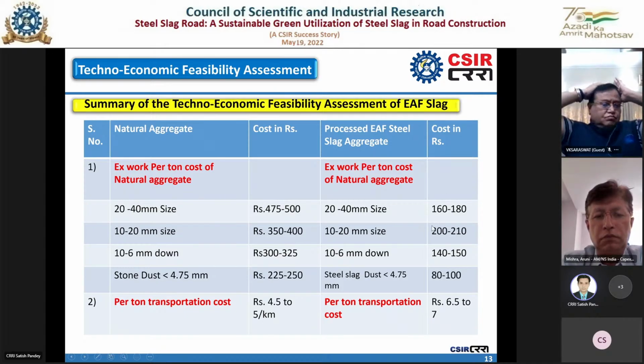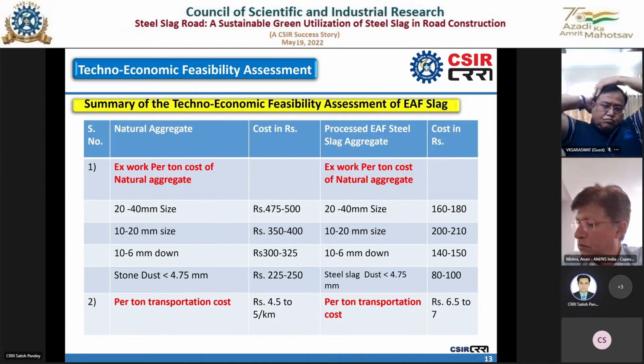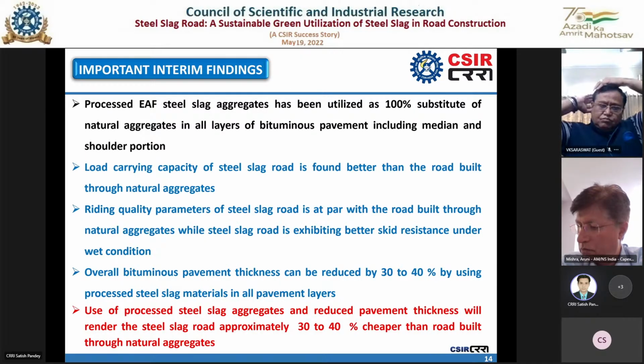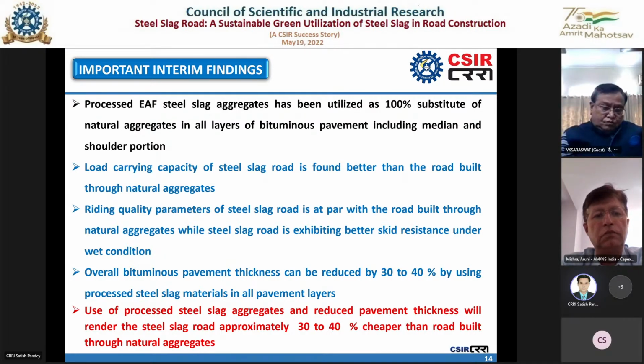So at last, this utilization is not going to become uneconomical, and in case we reduce the overall pavement thickness, then the road construction cost can be further reduced by 30 to 40%. One of the major interim findings of this particular study is that processed steel slag aggregate can be utilized as 100% substitute of natural aggregate in all layers of bituminous pavement, including median and shoulder portion.